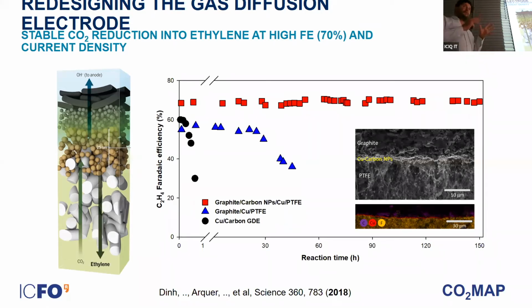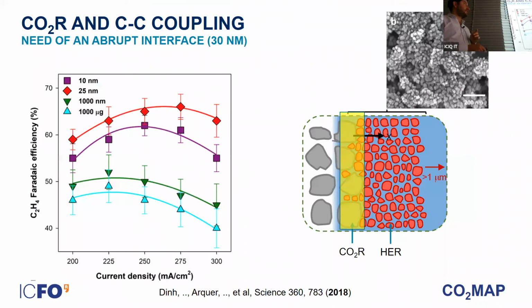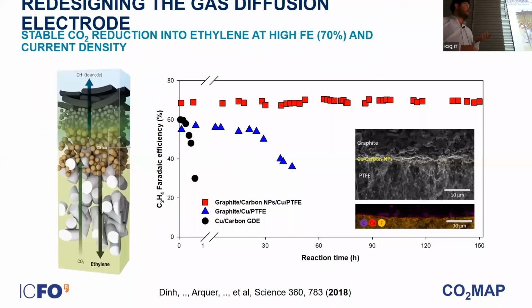So the way we were making electrodes before, we were just depositing copper on top of a carbon paper. And the reason why this didn't work is because hydrophobicity was lost and everything was flooded. And then all of these gas flow reaction conditions didn't work. It was as if you were just dipping your electrode, your catalyst in the aqueous kind of reactor.